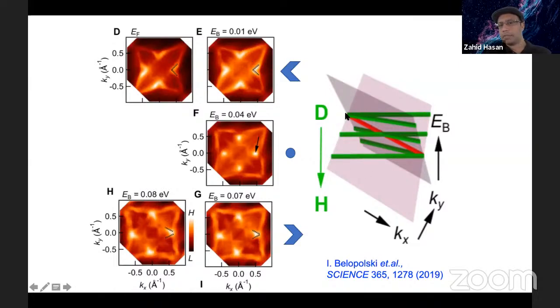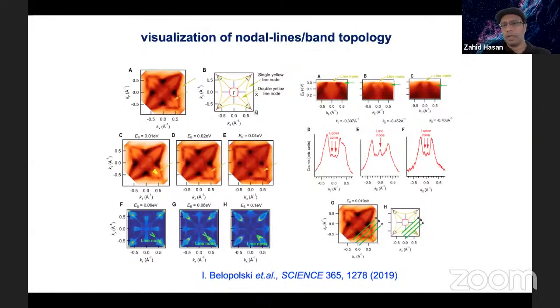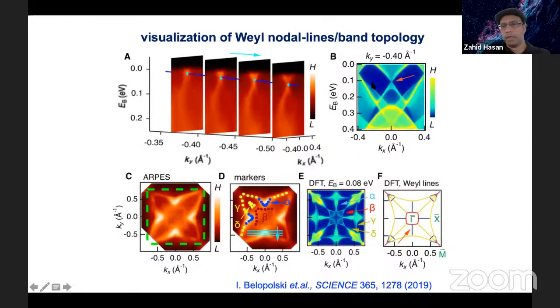Then we see that in the actual ARPES image, this part, and when we go to higher binding energy, we see this Weyl crossing, and then it moves away. So we use this type of construction, guided by DFT, to locate these Weyl points. By doing that all over the 3D Brillouin zone, we locate all these loops. One particular cut is shown here, where we can trace these Weyl nodes forming a loop and identify these various branches. But this requires polarization dependent ARPES, which we did not do here. Here we just use guidance from theory, DFT, to identify those branches.